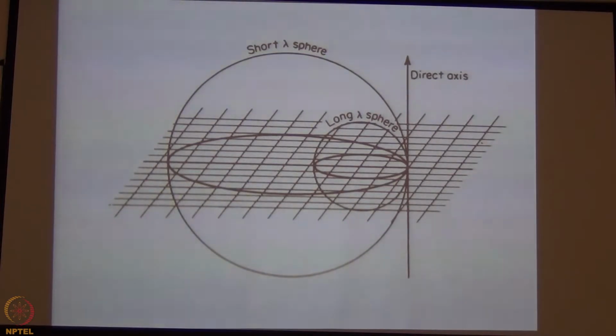How is the position of a reciprocal lattice point related to resolution? Smaller the d value, larger is 1 by d, further is that reciprocal lattice point from the origin. That means for a particular lattice, if you keep on chopping thinner slices with smaller wavelength, you can go to much thinner slices, much smaller d values.